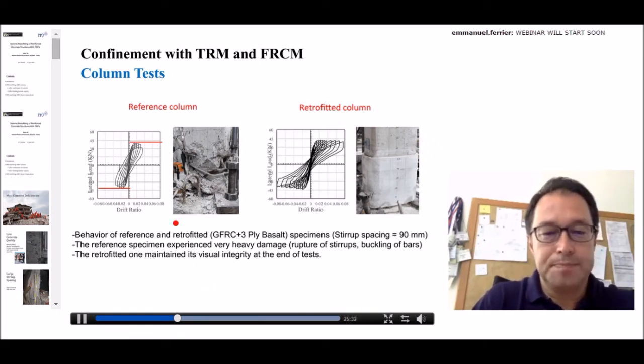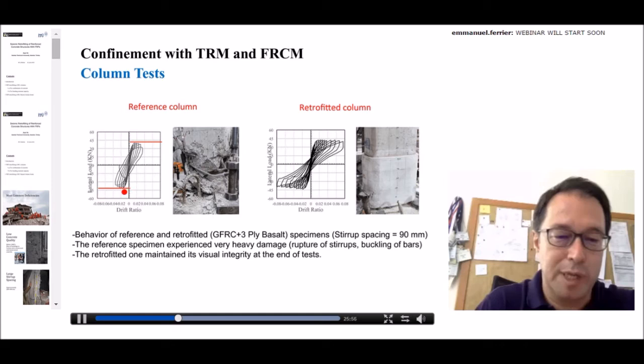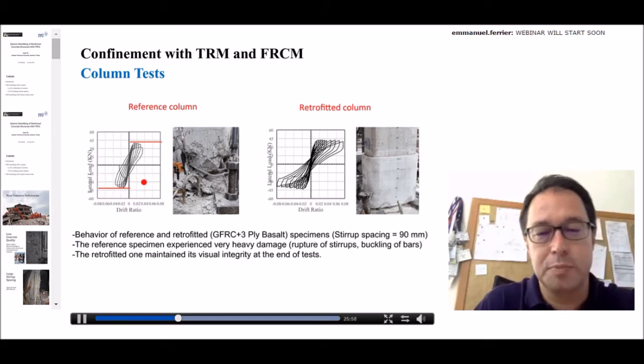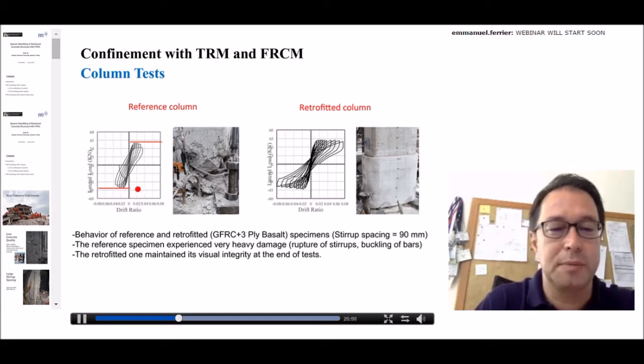So if you look at 2 specimens, on the left you see the reference column, on the right you see the retrofitted column. I should say that that is not the worst reference column because this column had stirrups with 90 millimeter spacing. You can imagine what the behavior would be in case of 80 millimeter space stirrup cases. It was much worse than this one, but in this presentation I'm showing these two specimens.